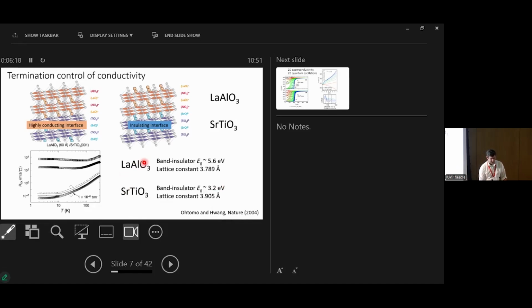But these two materials, when they made them, were insulators. And they put them together, and one of the interfaces, there are actually two choices, but one interface was highly conducting. So this is resistance versus temperature. It basically looked like a metal. If they made half a unit cell, so one atomic layer change to the structure, it was insulating.